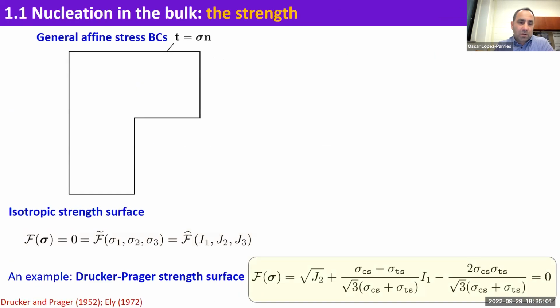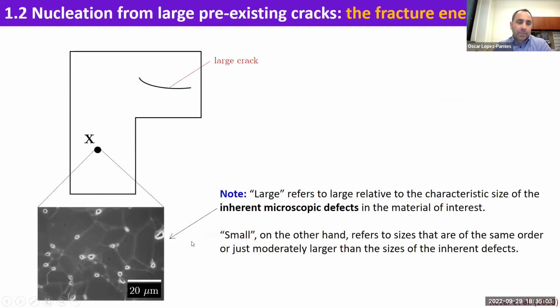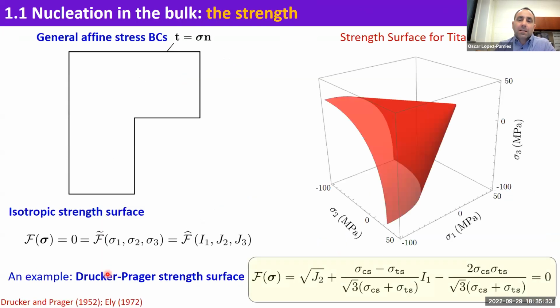of the inherent defects. This is a picture of a ceramic, much like alumina, where you can see that this was done through a sintering process, and therefore you have holes, let's say, in between the grains. You can see that these are random in size, in geometry, and all over the place. It is because of this that strength is stochastic. So one has to model strength stochastically. This is not a deterministic surface in stress space. It's actually a stochastic one.